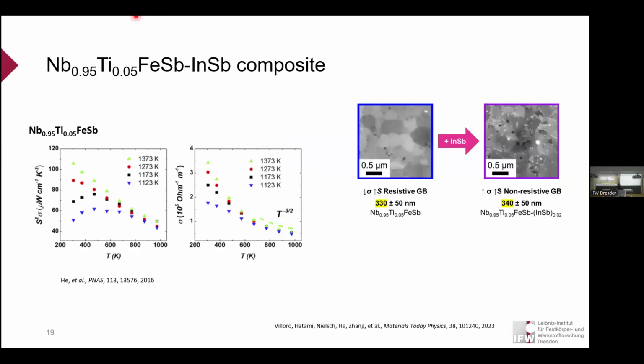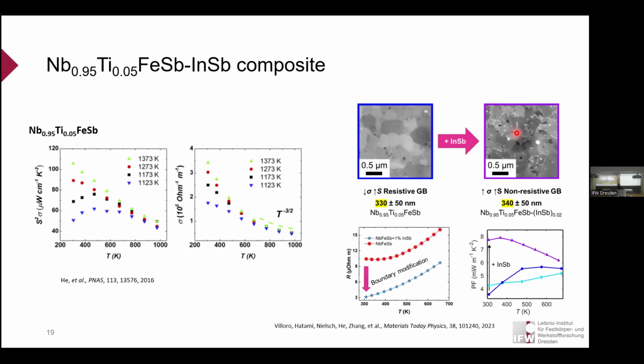We come up with the idea of indium antimony as a composite. For the same material and same processing, the grain size is nearly the same before and after adding the indium antimony half-Heusler phase. But this indium antimony does not really dissolve into the lattice. Instead, it forms particles and also aligns along the grain boundaries. This changes the microstructure, could yield a significant reduction of the grain boundary resistance of the material, and also increases the power factor.